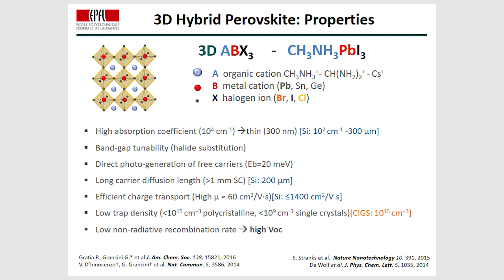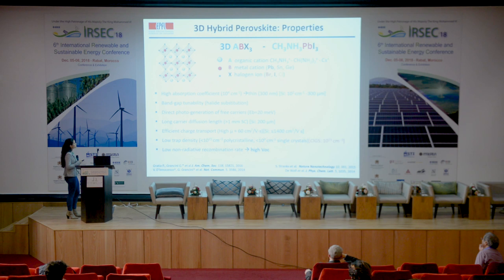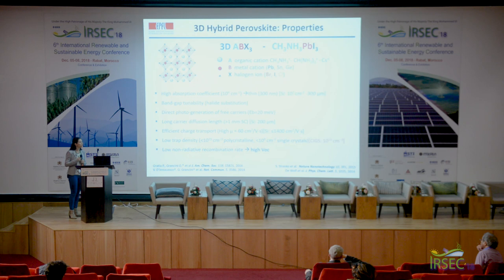Also represented by the letter B is the metal cation, which is typically lead — though other metals can be used in lead-free perovskites — and X, which represents the halide. This material presents really nice photovoltaic properties, such as high absorption coefficient, the possibility to tune the band gap, direct photo-generation of free carriers, long carrier diffusion lengths, efficient charge transport, low trap density, and low non-radiative recombination rate.